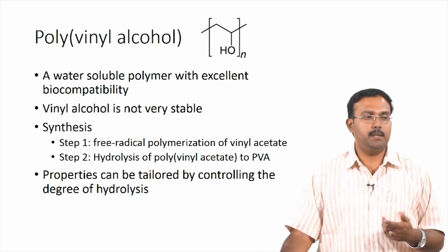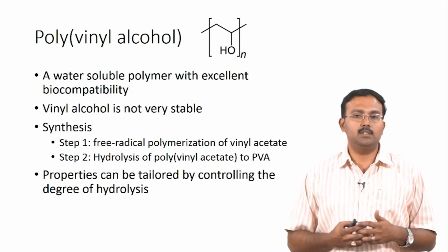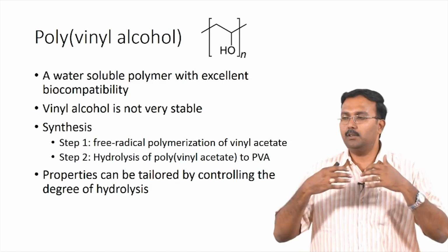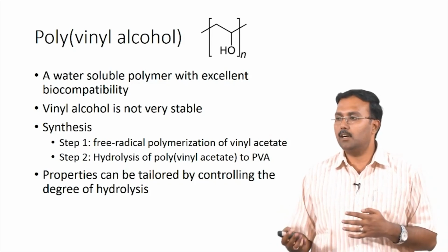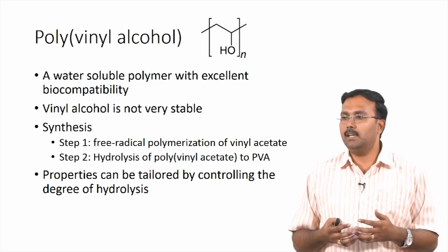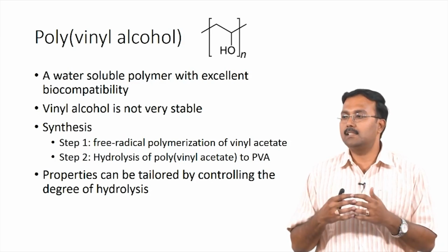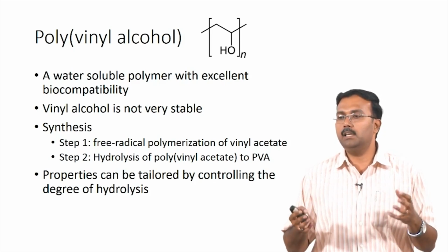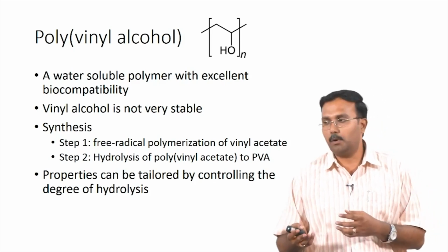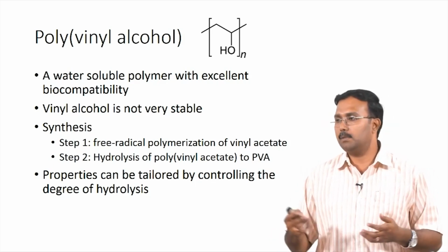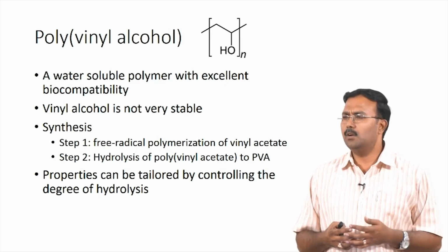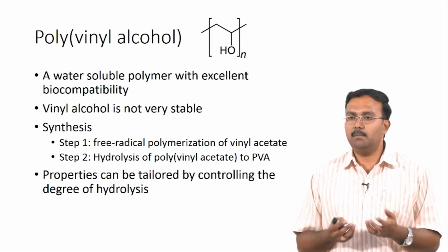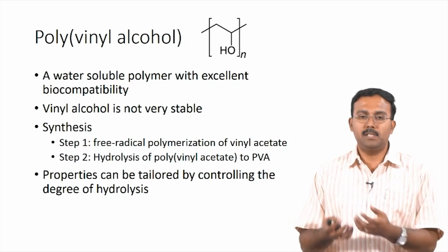The only limitation with PVA is it is so hydrophilic that it does not support cell adhesion very effectively. So, in some cases you actually need to maintain a balance when it comes to hydrophilicity and hydrophobicity. If it is going to be very highly hydrophilic, it does not support the cells as much as it should. Because of this reason people usually use it along with other natural polymers. Various types of natural polymers have been used along with PVA, cellulose and cellulose derivatives, hyaluronic acid, collagen, all these have been blended with PVA to improve its cell adhesion properties.